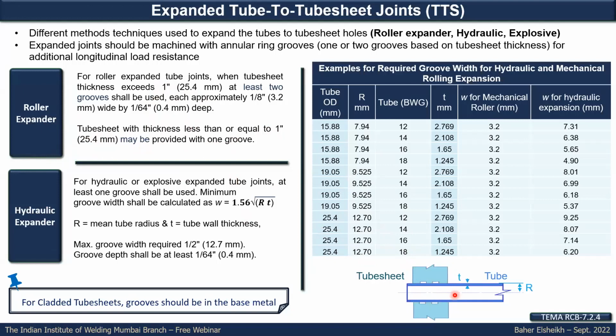For the roller expansion, against the hydraulic expansion, there is a different recommendation for the width of the groove itself. In the roller expansion, it is a fixed value like 3.2 mm, while in the hydraulic expansion, it is a function of the tube mean radius and the tube thickness. We will see this exercise in this table. We make a comparison for some different tubes with different thicknesses, of how much groove width might be required for mechanical roller or hydraulic expansion. You will see a major difference for the recommended hydraulic expansion.